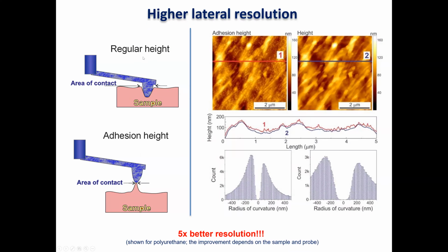Advantages of ringing mode. First advantage is higher lateral resolution. Regular height, for example, is defined, a resolution is defined by literally area of contact. And the adhesion height, for example, is literally when you have last moment of disconnection. So it's really small compared to the full developed contact.